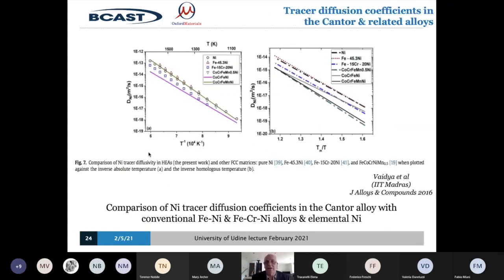The first one is the resistance to degradation of the material. Now, this depends upon how fast the atoms can move around in the material. We measure this by something called the diffusion coefficient D, and we normally plot D as a function of temperature on a D versus reciprocal temperature plot. So high temperatures on the left, low temperatures on the right.